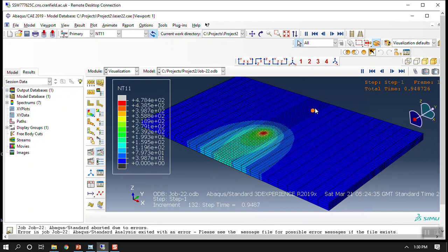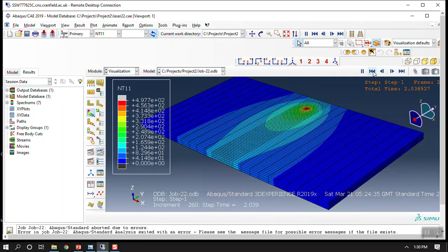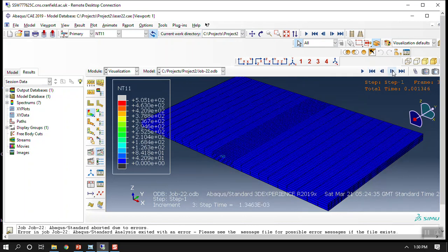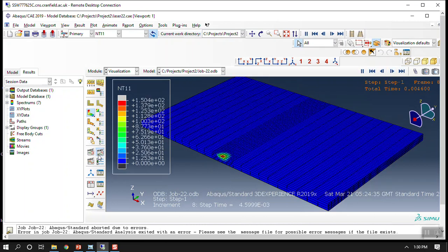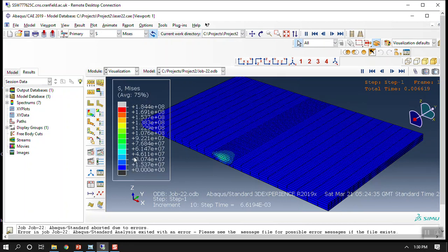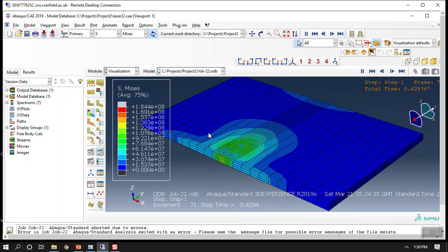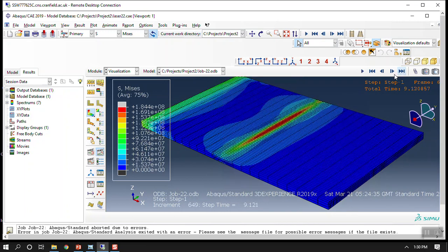I have done this model before, and I show you here that there is a laser moving on the plate, as you are seeing here. Because of this laser moving on the plate, this heat source, residual stresses are produced on the plate. If you choose Mises stress here, you see that after the process there is a residual stress of maximum 184 megapascal